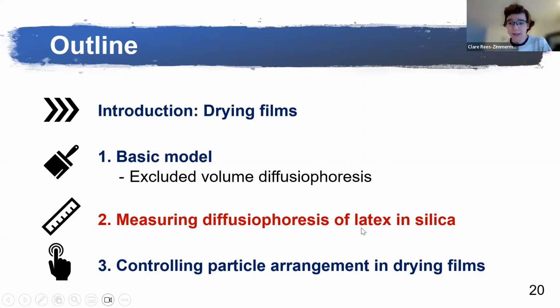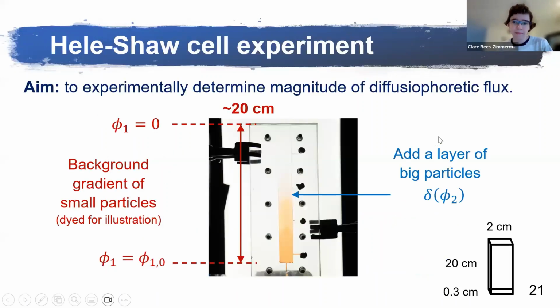I'm going to be looking at a dispersion of latex and silica particles, which are commonly found in industrial coatings. I run an experiment in a Hele-Shaw cell, named after Mr. Hele-Shaw, and this is parallel plates a few millimeters apart. It's commonly used for studying laminar flow. I set it up with a background gradient of small particles, which I've dyed red here for illustration, although in practice the camera can't see the small particles that I use.